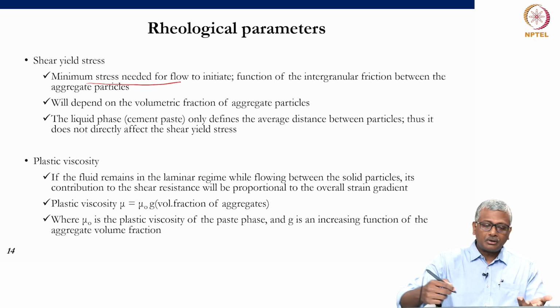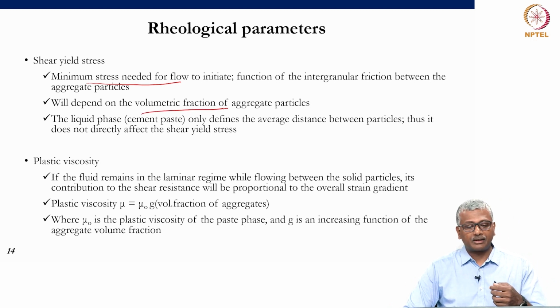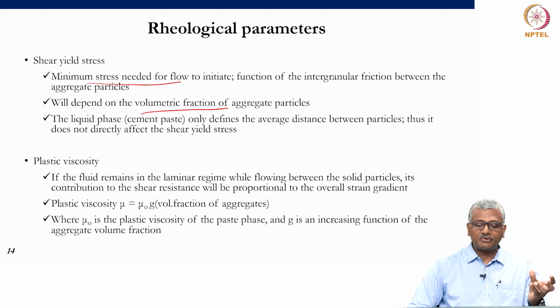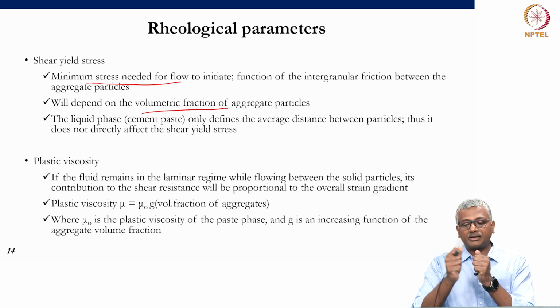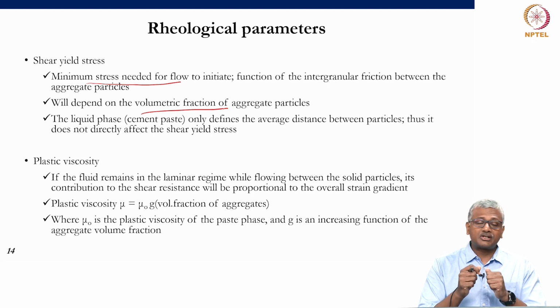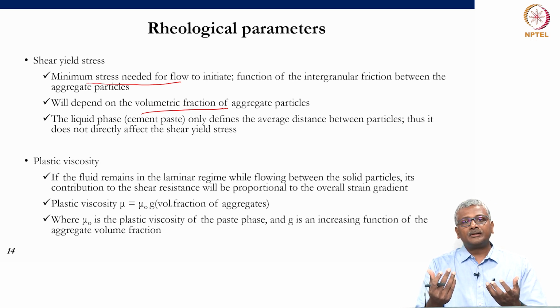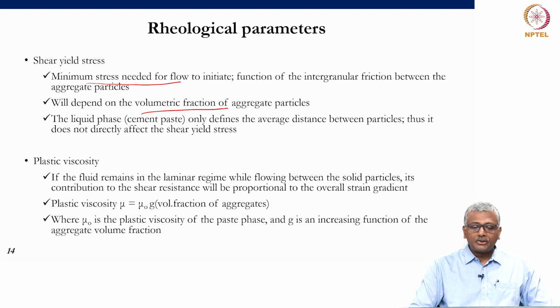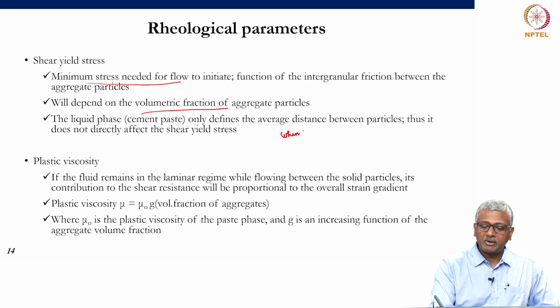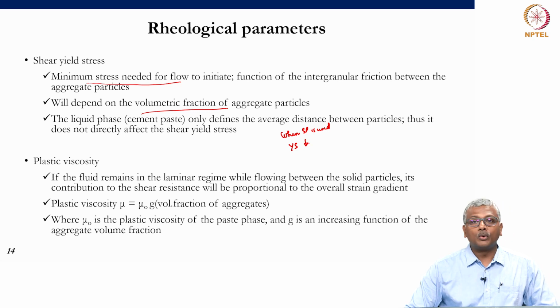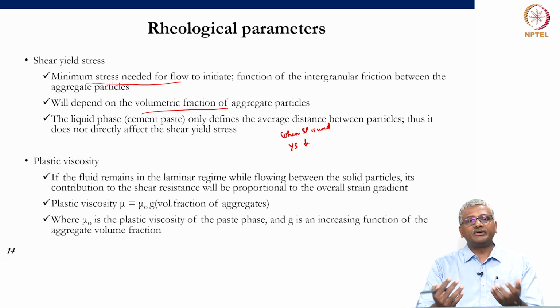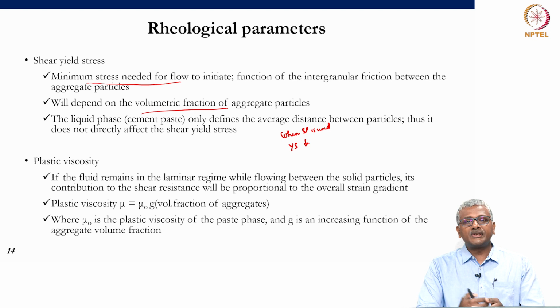Okay. So, obviously shear yield stress will depend on the volumetric fraction of the aggregate particles. The liquid phase, that is cement paste phase, it defines the average distance between the particles. Okay. So, it may not directly affect the shear yield stress, but when you change the characteristic of the paste, let us say when I add a superplasticizer, then the paste becomes so mobile that it is now able to push the aggregates much more easily, right. So, in such cases, when superplasticizer is used, yield stress gets lowered, yield stress becomes lower. But more often, the yield stress will become lower and lower when you keep on increasing the paste content and reduce the aggregate content.